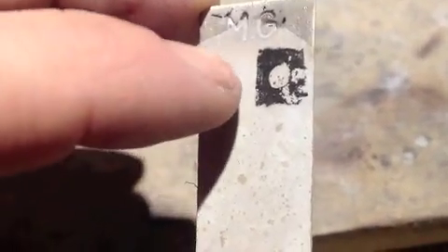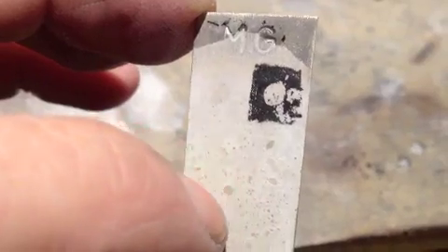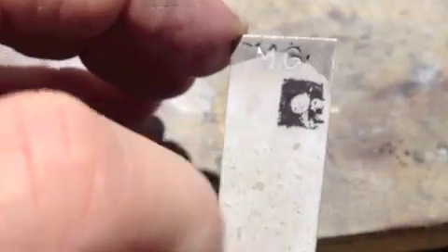Again, this is just a matter of trial and error, but suffice to say, the oxide layer does appear to be pretty tough and it did not eat through it with 38% phosphoric acid. I put a sample on last night and if you leave it on for an hour it definitely can eat through it, but at 10 seconds exposure, not so much. The efficacy of this remains to be seen for the long haul, and the integrity of how this material is applied is critical for the longevity of the cell. Have a great night.